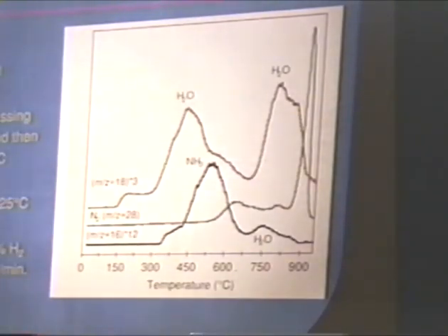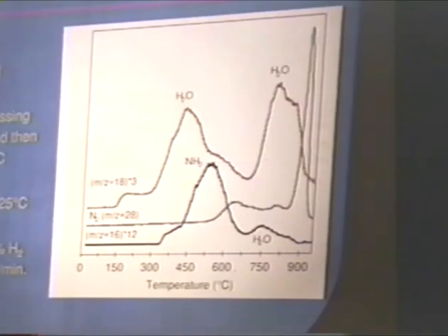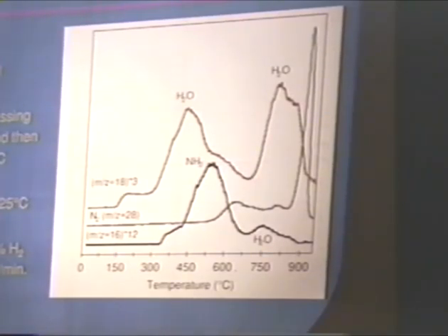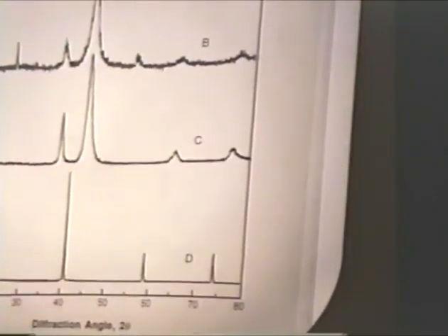Now, what is more interesting here is a high temperature and a very sharp nitrogen signal, and this corresponds to the decomposition or destruction of the nitride structure altogether. So if I go back and look at the X-ray diffraction spectra that I mentioned, the top pattern corresponds to a sample which has been passivated, and then we are looking at a sample which has been activated.